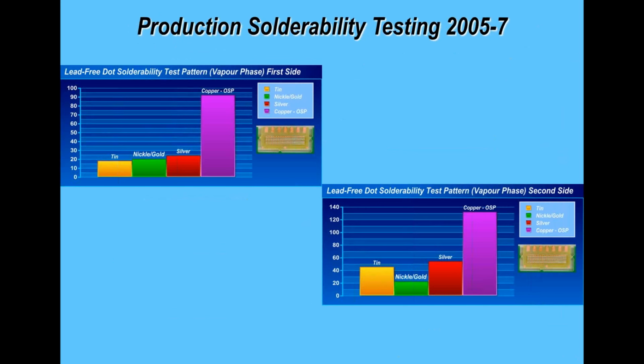Now, the two graphs I'm showing you, first of all, is on vapor phase, and you can see how the number of dots increases based on the performance of a particular finish. Now, if you look here, tin is pretty good. After first reflow, you've only got an average of 20 dots that haven't coalesced, whereas you've got nearly 100 for OSP. But after second reflow operation, see how the tin changes in terms of dropping its soldering performance.